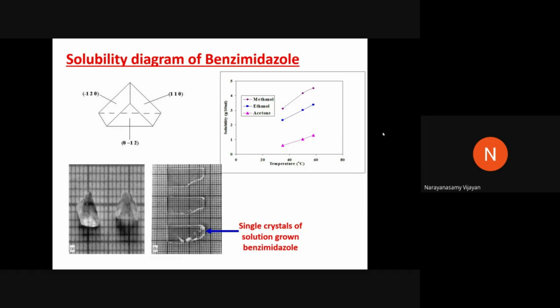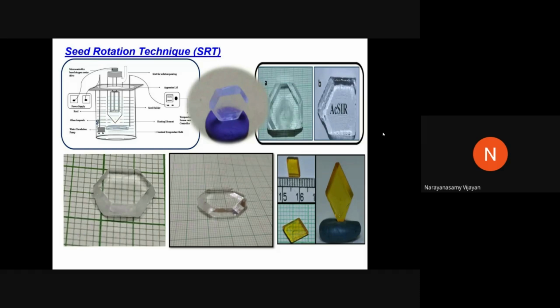Why have I chosen these single crystals? I have grown this single crystal by 3 different techniques. Now you can see this is the maximum size one can grow by the slow evaporation solution growth technique. In addition to that, you can see different facets. Different facets have different directions. Each and every direction will show a different value of nonlinear optical efficiency. So I will come later to how I have grown the same crystal with a single direction and how I made it a very big single crystal of benzimidazole by the melt growth technique. Maybe in a later slide I will explain.